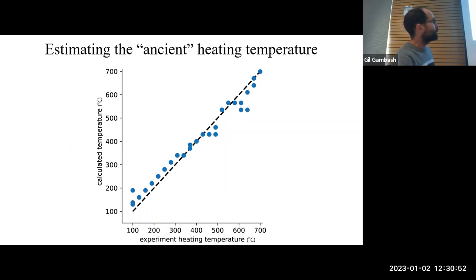Maybe in the lower temperatures it's a little too high, and here maybe too low, but we're up to 30 degrees Celsius off on average, in every temperature step, which is, I think, a very good estimate for the ancient heating temperature. So now we have a tool that can also identify burnt materials from 100 degrees and up. I think from about 200 degrees and up it is really reliable; between 100 and 200, it's sometimes hard to tell if it was burnt or not. But it's very reliable from 200 degrees and up, and can also reconstruct relatively accurately the heating temperature.